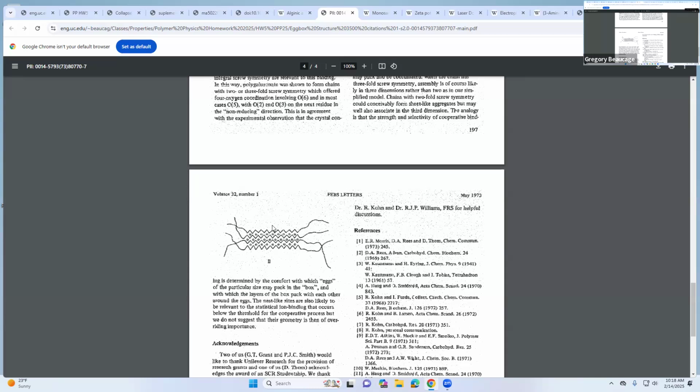So you can precipitate it out with calcium. Divalent cations have 2 arms to link with, so they can be a cross-link site if they can find anions on the polymer to hook to. Monovalent ones just stick on, they can't do anything. All right, so the divalents are going to make a gel, and monovalents are going to just mess with the Debye screening length things.